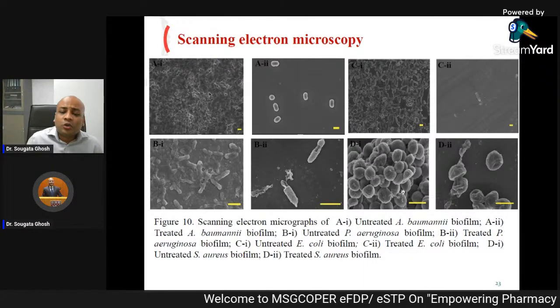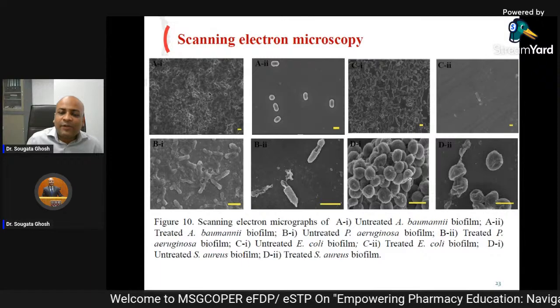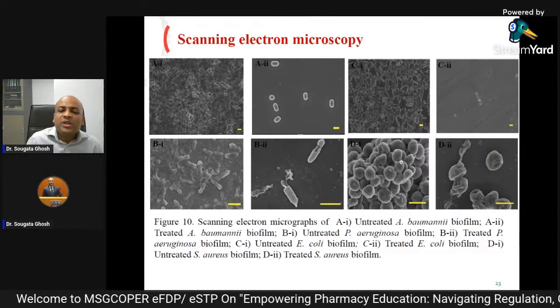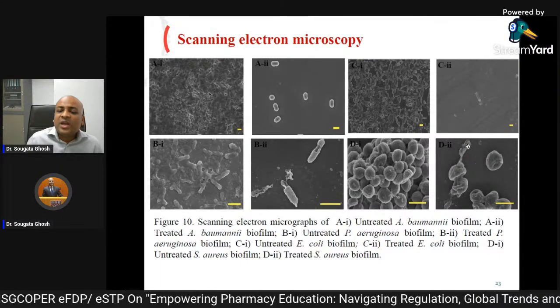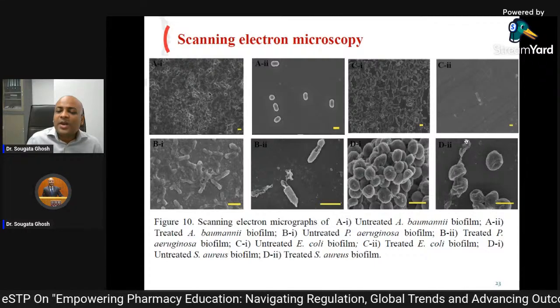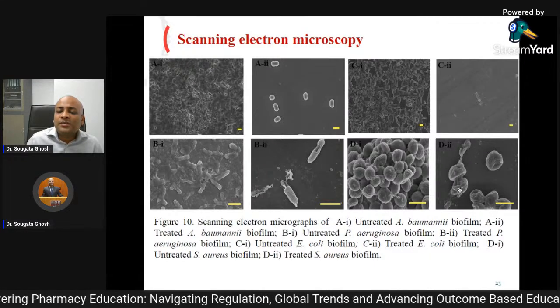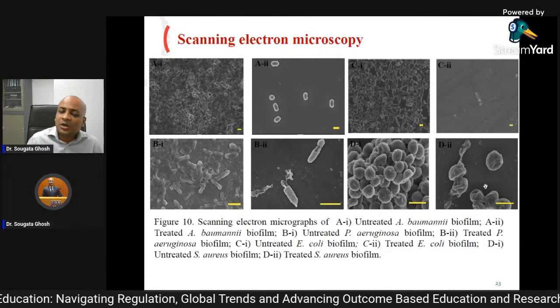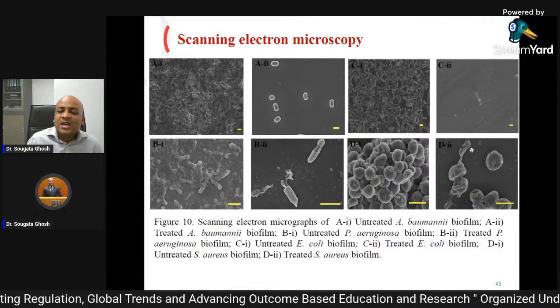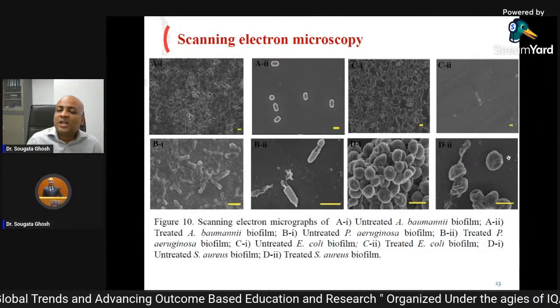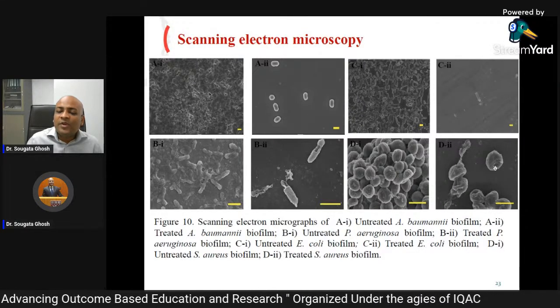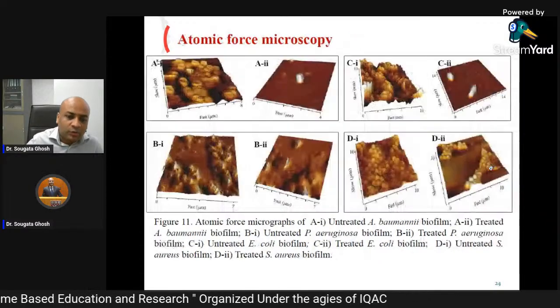This is Staphylococcus aureus, a very intact Staphylococcus aureus biofilm. We treated with our nanoparticle. You can see the cell wall damage. The inner contents are all coming out over here. So there is complete damage, and you can see the exposure of the surface. The biofilm is eradicated. It is white.